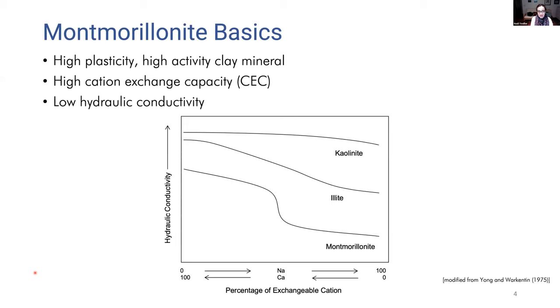Montmorillonite is a very highly plastic, high activity clay mineral. It has a high cation exchange capacity and a low hydraulic conductivity. The graphic in this slide is a schematic representation of hydraulic conductivity versus percentage of exchangeable cations that may be present in the exchange complex of a clay mineral. And we have data shown for kaolinite, illite, and montmorillonite, the three common clay minerals. If we look at montmorillonite data, we see that the hydraulic conductivity is the lowest when the material has the highest amount of sodium in the exchange complex. As the amount of sodium in the montmorillonite increases, hydraulic conductivity decreases, and the reverse is applicable for calcium.